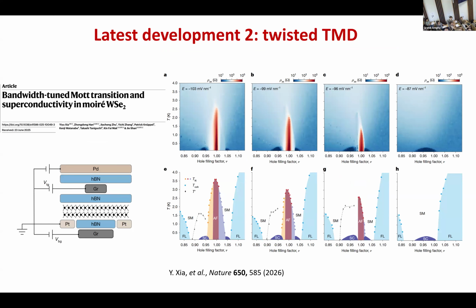The other one is also about twisted materials. People move from twisted graphene to something else, like twisted tungsten diselenide. And I was quite amazed by this because I was working quite a lot on high temperature superconductors, cuprates. When I looked at this phase diagram, this was like a dream for high temperature superconductor people, because with one sample, you could tune these parameters and go through the whole phase diagram just by tuning some voltages. You can see that this phase diagram looks pretty much like a high temperature superconductor, with this antiferromagnetic phase, and then you get the superconducting dome, and also you have some strange metal, and then at higher doping you go to this Fermi liquid phase. So this is also quite interesting.